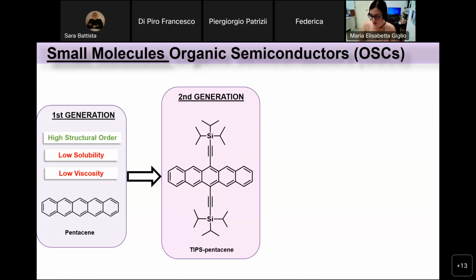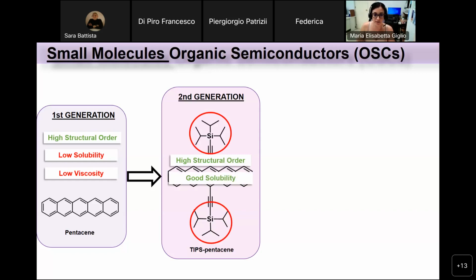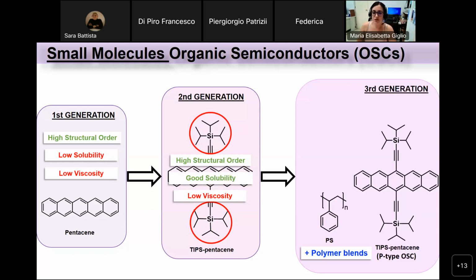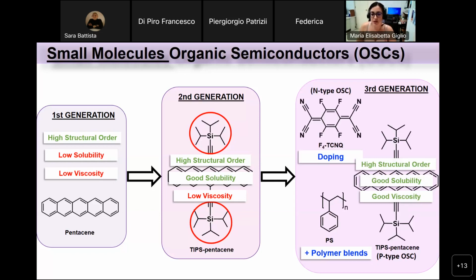And then the second generation of this kind of molecules is represented by TIPS pentacene, which basically has the same properties of high structural order, but in addition has very good solubility due to the new functional groups that have been added to the pentacene structure. However, it's still low viscosity in solution. And then the third generation of this kind of materials is represented by the blending of, for example, TIPS pentacene with polymers such as polystyrene, which adds the good viscosity in solution. Moreover, we have other kinds of molecules that can be added to TIPS pentacene, which is a p-type organic semiconductor, as dopants.